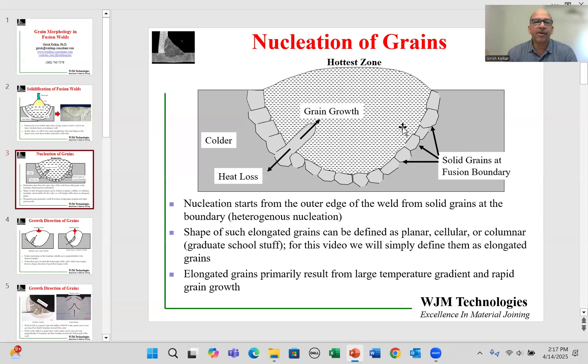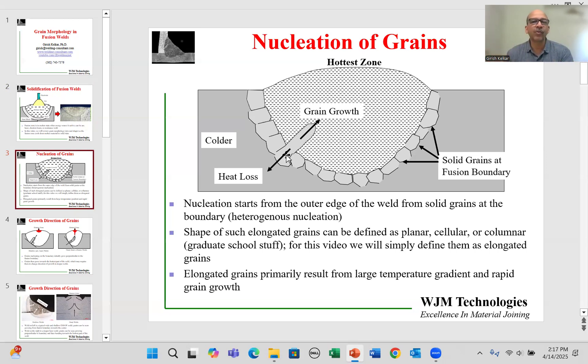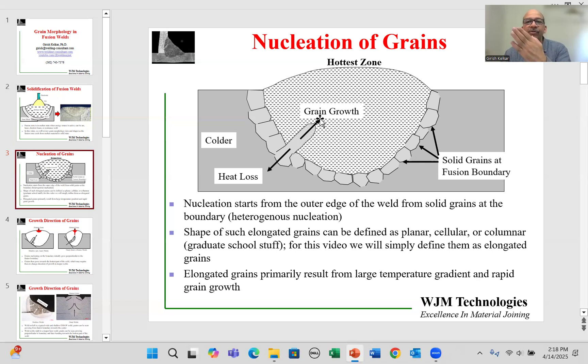Here I'm showing you a schematic where the arc has been turned off, but still the hottest point or hottest zone in the weld is going to be right where the arc was active. You have the molten metal zone, and you have the solid metal around it, and this boundary is called the fusion boundary. Once the heat has been turned off, there's a rapid loss of heat through the base metal and the weld starts to cool down. During this process, grains start to grow from the outer edge of the boundary and they grow into the weld. In this particular schematic, I'm showing you a single grain which has been initiated from one of the grains right on the boundary, and the grain is growing in the opposite direction into the fused metal.